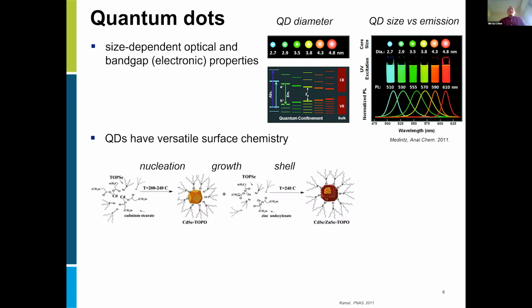In terms of surface chemistry, this is a very important property of these materials. They can be easily synthesized. I will not go into details, but basically they are synthesized out of atoms connected with ligands. So through nucleation, the core can be grown. In this way, we modify the optoelectronic properties, and then we can create shells around the quantum dot. And these shells are very important, one, for protecting the quantum dot's optoelectronic properties, two, for connecting the quantum dot with the outside world. And when I say outside world, it's something like, for example, what we call acceptor material.